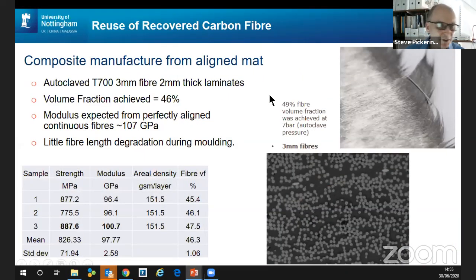With this process, we can get some very high degrees of alignment, and at autoclave molding pressures, we're able to achieve fiber volume fractions of 46%, and with 3mm fibers, making some 2mm thick laminates, we were able to achieve a high modulus of around about 100 gigapascals, over 90% of what you'd expect from perfectly aligned virgin fibers, and you can see a cross section here, and all the fibers are packed together fairly well and all fairly well aligned.